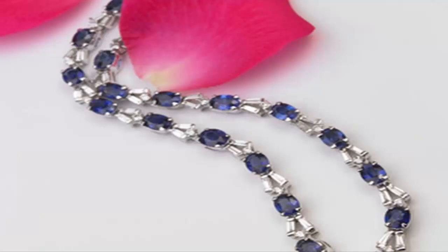Choose the temperature and exposure time carefully. Heating sapphires at too high of a temperature for too long may irreparably damage the gems, as noted on the website Gemstone Buzz. Cooking a sapphire at 1600 to 1800 degrees Celsius for 2 hours intensifies blue and yellow colors while removing silk.